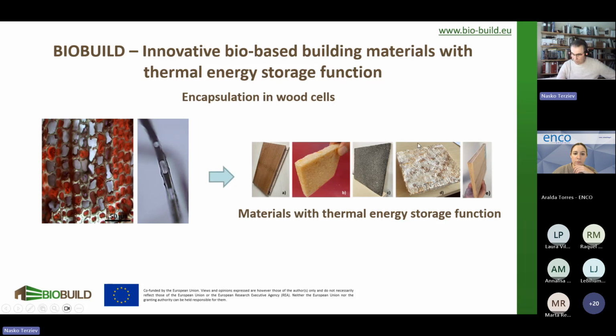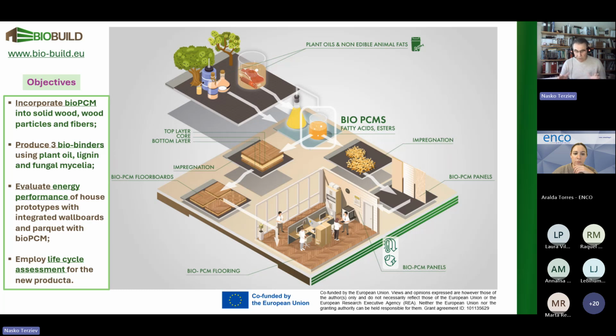We have also 4 different materials, which contribute to the entire project idea. In the beginning, we select the phase change material, a biological phase change material, which is extracted from plant oils or uneatable fats. Then we impregnate it in, let's say, the core of the flooring. This is one product. And then we have wood fibers or particles which are impregnated with the phase change material to build wall panels with 3 different technologies. One of the technologies uses plant oil as a polymer for binding. The second uses lignin as a binder, and number 3 uses fungal mycelia also as a binder of the panels.